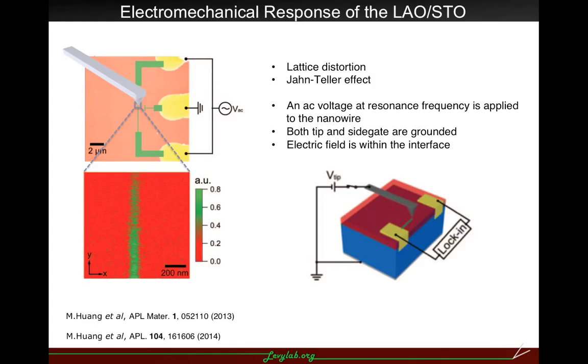A specific piezo force microscopy has been performed to study the electronic nanostructure created at the LAO-STO interface. A side gate and a single nanowire are created by lithography techniques. While doing the PFM, both the tip and the side gate are grounded, eliminating any electric field applied across the LAO and STO layer. And an AC voltage at the resonance frequency is applied to both ends of the nanowire. In this way, the electric field is only within the interface. The PFM piezo response comes only from the change of the carrier density.